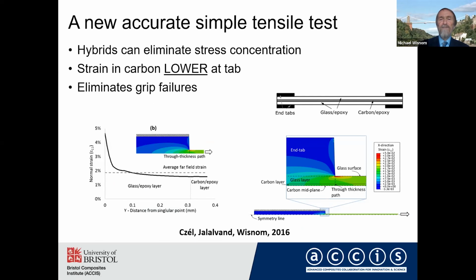And the reason for that can be seen by doing an FE analysis. So if you do the FE analysis across this here, you'll find that actually the stress in the carbon is lower than the nominal stress. And then you have an increase here where you go into the tab. And the reason is that by equilibrium, the total load has to be the same across that cross-section. So you have a stress concentration here in the glass, and the stress in the carbon has to be actually lower. And as a result of that, you completely eliminate grip failures, and you can get a true gauge section failure, which is unaffected by the gripping condition. So I think this is very promising.